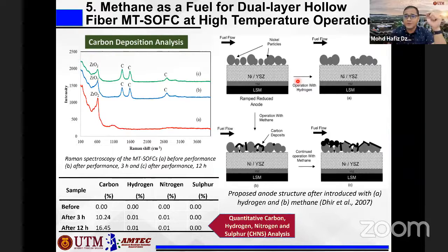Because normally for the anode you use nickel, and nickel is very prone to carbon deposition when you have hydrocarbon fuel as the feed. Okay, so when you expose it to hydrogen, the structure is still the same because there is no carbon deposition. But when you expose it to methane, carbon deposition will take place, and it will cause structural changes in your anode, and therefore it will cause cracks in your cells. Therefore, after a few hours, your performance has already dropped.